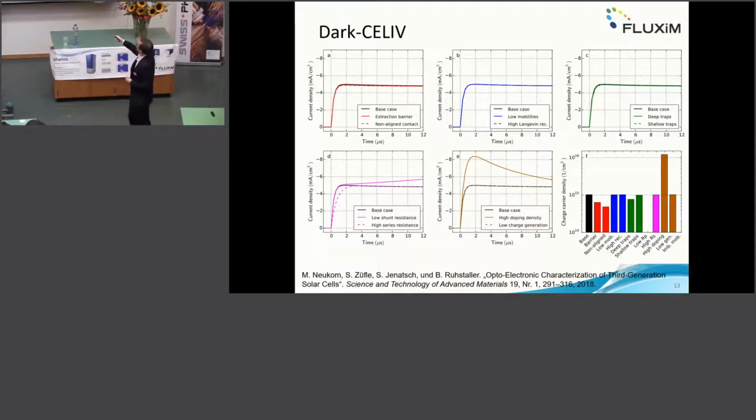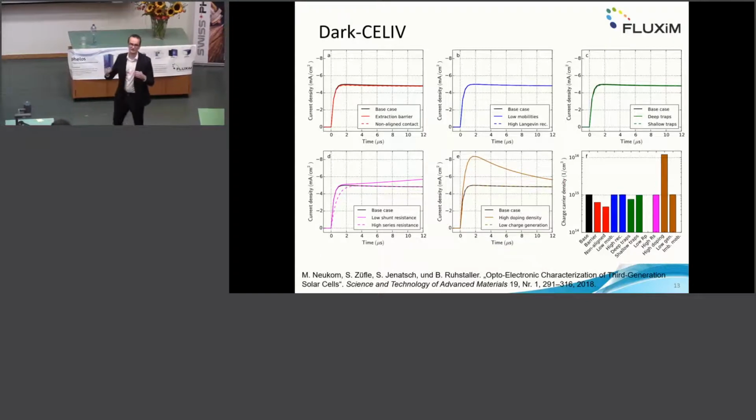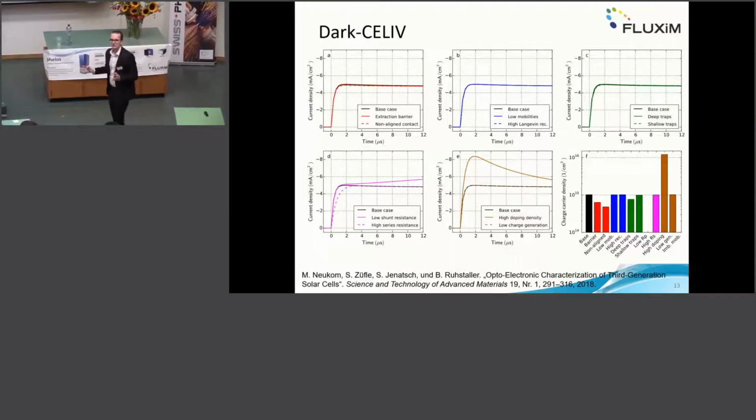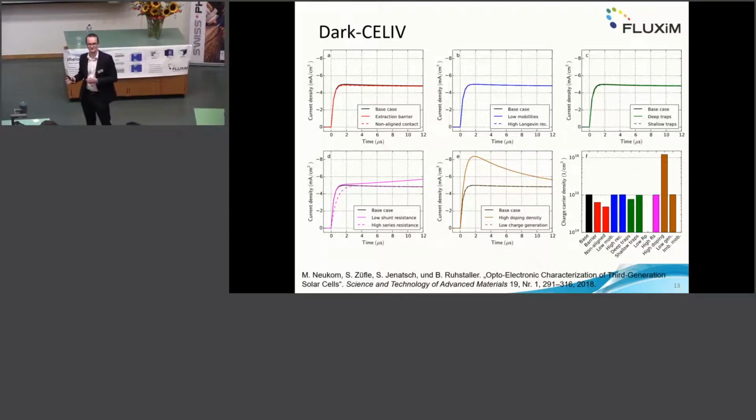In the lower case, there is one case where we extract something, and it's the case of high doping density. You see there is a peak and there is charge being extracted. So what one can do is integrate this current over time to get a charge, and divide it by your device volume, so you can estimate the doping density. Here we extracted about 10 to the 16, but it's much lower, because what we put into the simulation was 10 to the 17. It's quite clear that with this experiment, we cannot extract all the charge that was in before.